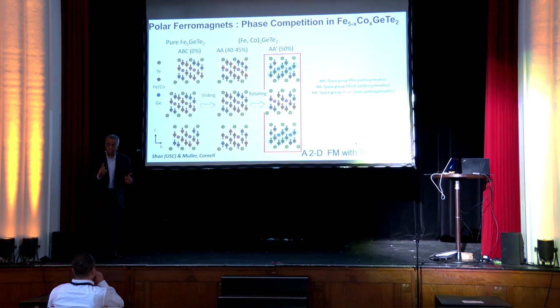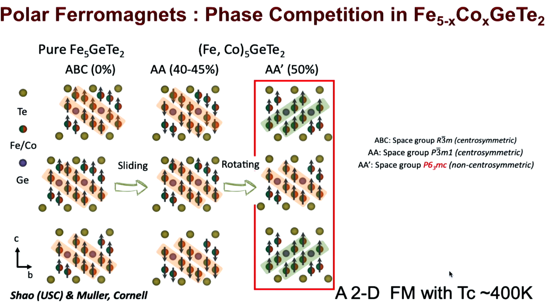Okay, so the first example, there are a few examples in the beginning, just to show you how, you guys know these systems very well. The 2D materials are all very well known to this community. The one example that we've been working on for about 4 or 5 years now is this iron germanium tellurium system. It's formally a 2D kind of system. The bonds in between the tellurium atoms are relatively weak, so it behaves very much like a 2D system. The interesting thing in this system is that as you start to put cobalt into the system, it goes through a series of phase transformations.